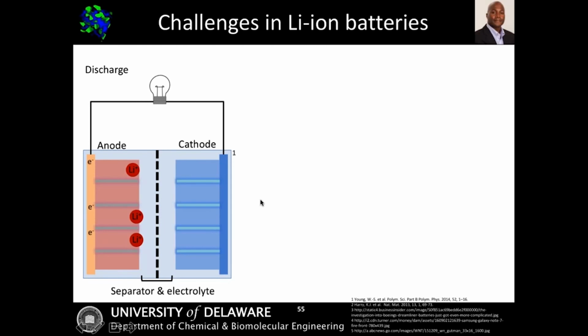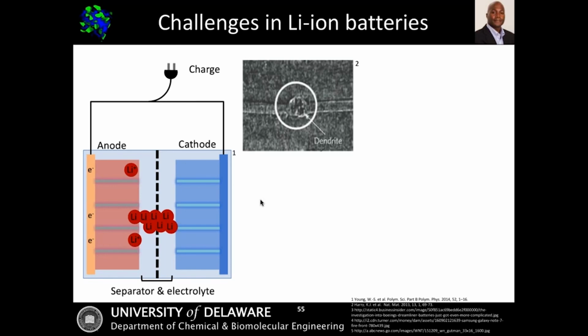Think about this: we've got an anode and a cathode and then the electrolyte/separator. In this case, we get our discharge cycle, where we get lithium migration from the anode to the cathode. We can also do charging again. One of the issues associated with charging is that we can get dendrite formation, which can lead to some of the failures and issues associated with batteries. We're all aware of those types of things happening. For example, here's one example of dendrite formation, showing a lithium metal dendrite that can propagate across a typical polymer-based electrolyte.